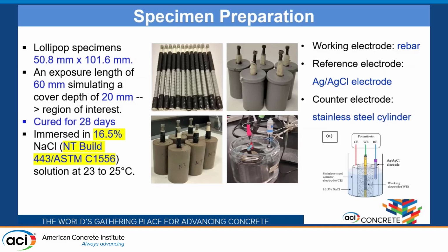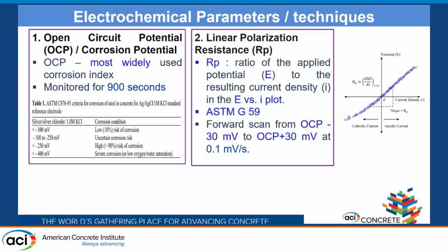However, to conduct corrosion testing, we need to have this 3 electrode setup where the rebar acts as a working electrode, and a silver/silver chloride electrode acts as a reference electrode. So this is a sample figure of our electrode setup, which is then connected to a potentiostat to get all the readings.